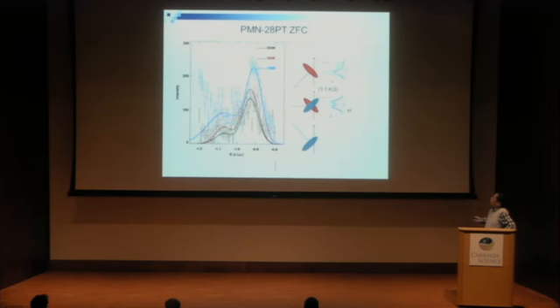And also, we did some temperature dependence from 100 to 500 K. The intensity increases with cooling, but even at 500 K, which is above Tc of around 375 K, the diffuse scattering intensity is still there.